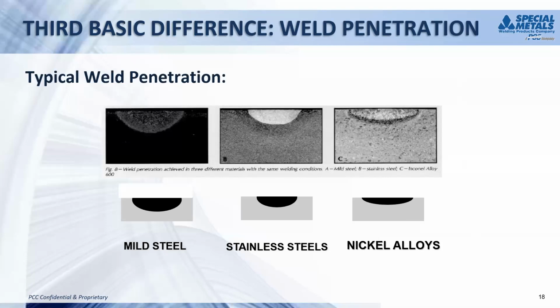I remember when I was first learning to weld in the weld lab, the guys had a plate set up for me. They threw the weld rods down on the table and laid a grinder there and said, if you don't make any mistakes, you won't need this grinder. And you can imagine how many mistakes I made. But one of them was from trying to burn out. If you have a tight groove that you've created by a rolled over bead, you cannot burn that out like you do with steel. So you have to grind it, open it up. And we'll talk about that in difference in joint designs.